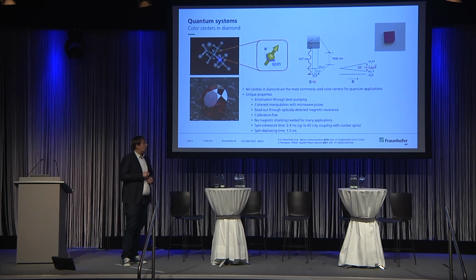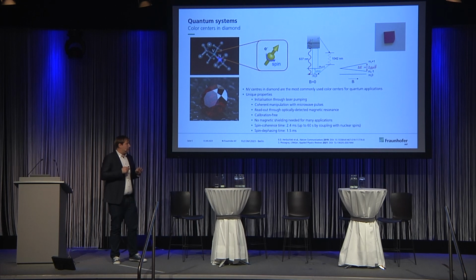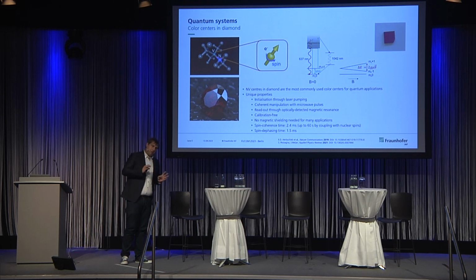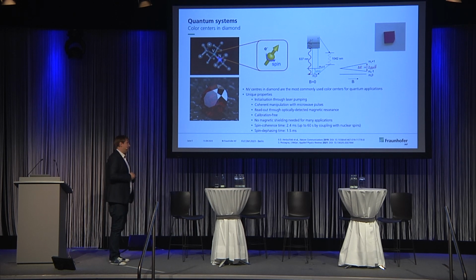If it's in the MS0 state, it will be at a constant level, and this also leads to this nice red color of diamonds with lots of NVs. This is actually, the image here is not the true size. Typical diamond substrates are 3 by 3 millimeter, maybe 5 by 5 millimeter, but not wafers.